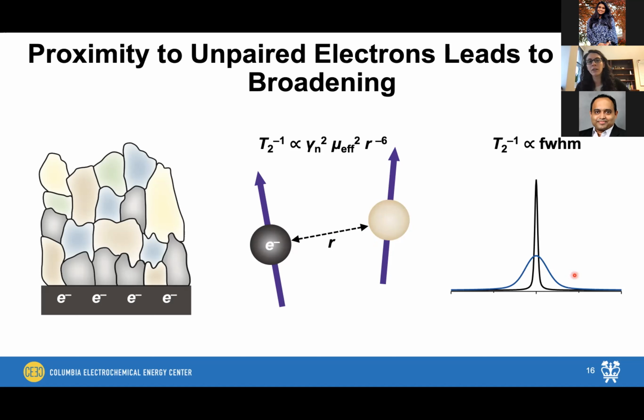Oftentimes in solid state NMR, in order to get high resolution spectra, we're also going to be mechanically rotating our sample. And because we're mechanically rotating our sample, we get something that's called a spinning sideband pattern. So this very broad line shape is also going to be broken up into this spinning sideband pattern that looks something like this, where we get a peak that coincides with our normal isotropic peak that we would expect for lithium carbonate. But then it's going to have this sideband manifold that is sort of enveloped by this very broad NMR line shape that's coming from coupling to this unpaired electron from the paramagnetic material that's underneath it.